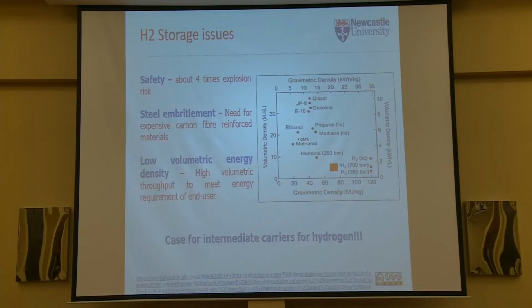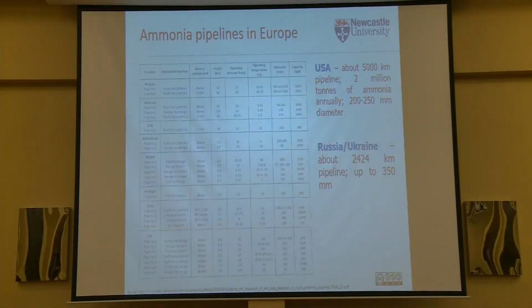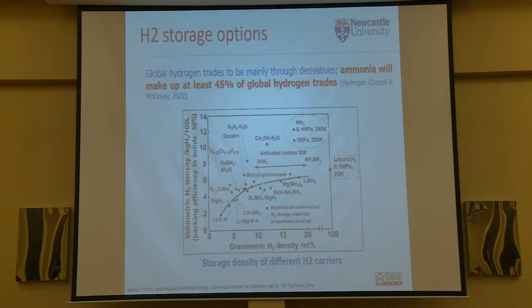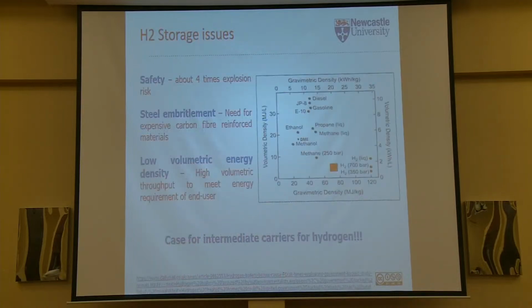Now, if you take a look at this portion of the graph, you will see that for instance, liquid hydrogen, the storage density is around 2 kilowatt-hour per liter. Now, if you compare that with, say, diesel, you see that the storage density is around 10. What that means in principle is that to transport the same amount of energy that you would get with a given quantity of diesel, you would require roughly 5 times the storage tank.